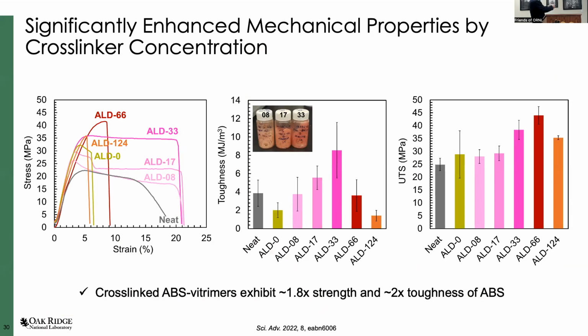Again, these are the tensile curves showing strain versus stress. The stronger material goes much higher in strength, but overall you want a bigger area to make it a tougher material. The starting material is the ABS neat, like this. Once it's cross-linked, this ALD 33% amine cross-link, that's what it means. This shows the trend of toughness going up. We varied the ratios of the cross-links, and 33% was the best ratio, so we stuck with it. This goes from 25 megapascal here to 40 or 45 megapascal. So it's pretty much twice as strong, and also a tougher material.